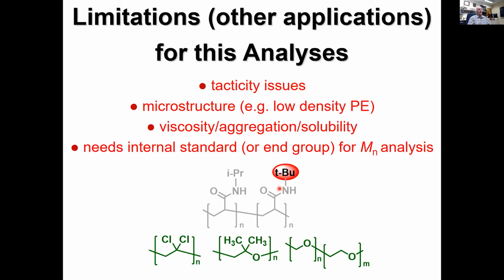In an NMR tube, they start to aggregate and you start to see just broad spectra. So even if you could look at this tert-butyl group, because the methyls are relatively far away from the place where the tacticity is, that really doesn't work.